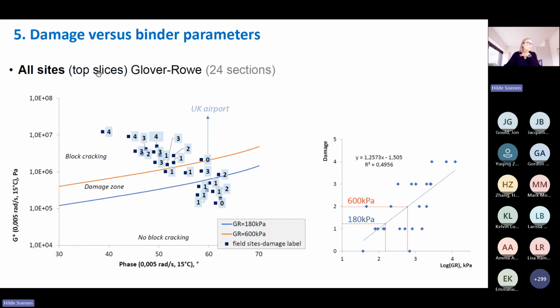The next graph here is now all the sections, the 24 sections. So you see again, there is quite a correlation. There is one exception here, which, if you do it statistically, is seen as an outlier, but in fact, this is an airport pavement and it is a highly modified binder. So probably that is the reason why it is an outlier. If you look in the graph damage versus logarithm of Glover-Rowe, it is the point here, which is in fact the point which makes the correlation a bit worse. But still we are at about 50%, which is a lot if you consider all the variations here.